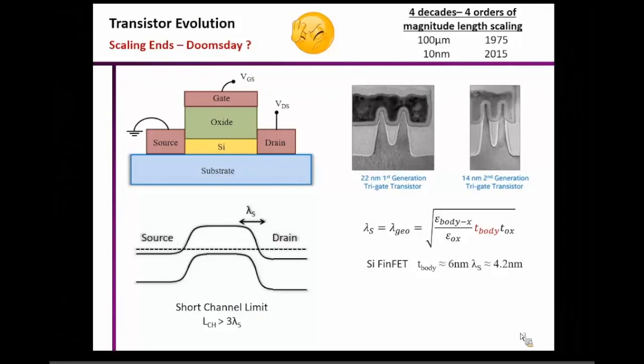And this has been possible with silicon technology, and you can see the current Intel's 22 nanometer first generation Tri-Gate and the 14 nanometer second generation Tri-Gate transistors. This has been mostly possible because our channel length has mostly remained less than 3 times this length scale that I call the screening length or the geometric band bending length. It depends upon some material parameters listed here, like the thickness of the oxide, the dielectric constant of the oxide, and also the thickness of the silicon film that we're using as a semiconductor.